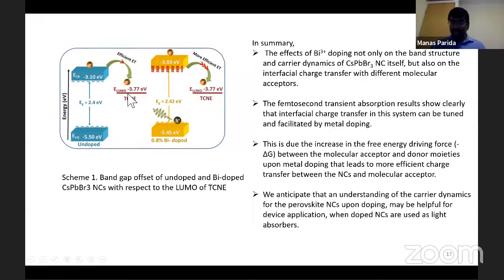So that means, due to the increase in the driving force, if you see the band, this one is minus 3.1, this is minus 3.03. So definitely, because of the presence of trap states on the surface at the higher excited state, you have a clear energy difference between the conduction band here and the LUMO level, and that's why you have a more efficient electron transfer. Okay, so this is how the carrier dynamics, or the electron transfer process, happens, because you have to understand how it will be used in a device when you make the device. So in the presence of doping you have more efficient electron transfer due to the change in the driving force, which is the Gibbs free energy, which is more here compared to the undoped one.